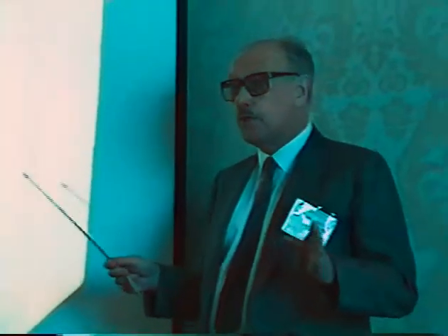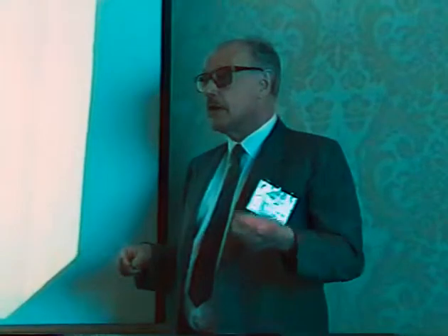That is different for other systems. We have also studied rhodium-iron, where iron is in part reduced so that you get an alloy. Also in palladium-iron you get the alloy. But in the manganese case, this is not the case.